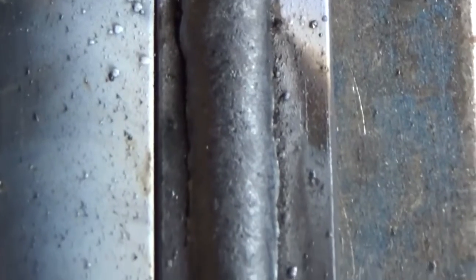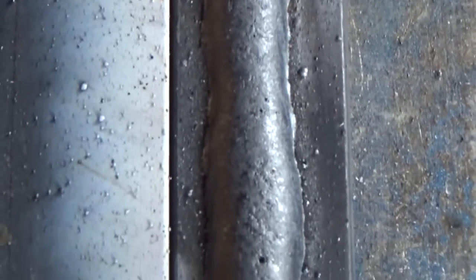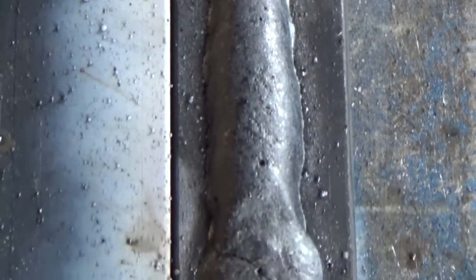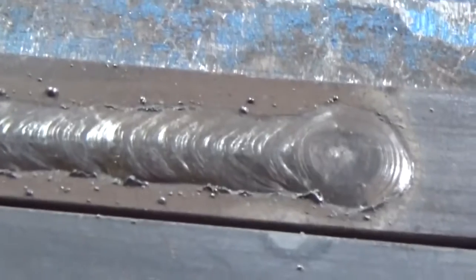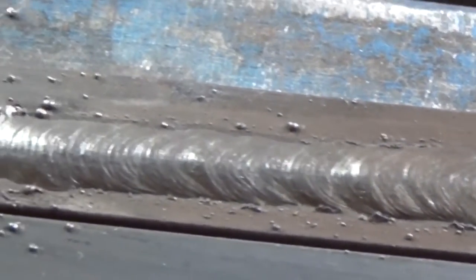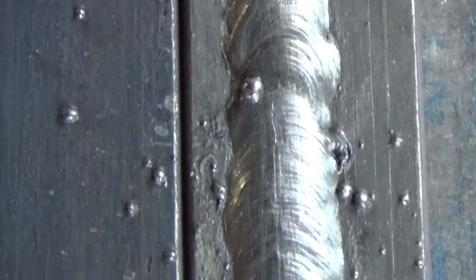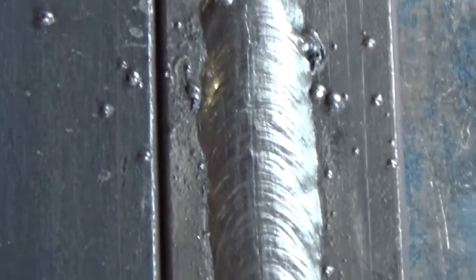And finally the third weld: rutile coated electrode, negative, current is 95 amperes. Look at the fact that the puddle is very fluid. It's difficult to manage. Metal excessively spreads over the surface. Quite a lot of large and small spatters are produced around the weld. Welding with this current is very fast. The arc is very bright. Clean off the slag and inspect the weld.